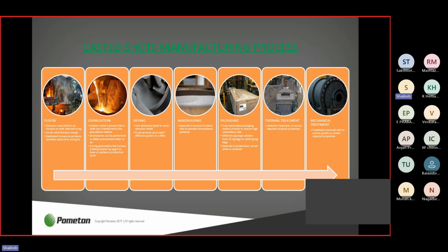So the first step of the manufacturing process is fusion. In this process, all the alloying material and scraps like iron, chromium, nickel, whatever the grade of sorts we want to manufacture, is fused in an electric arc furnace. These furnaces have a minimum capacity of 15 to 20 tons at one charge. All the alloying materials are melted in the electric arc furnace, and then it goes for granulation.